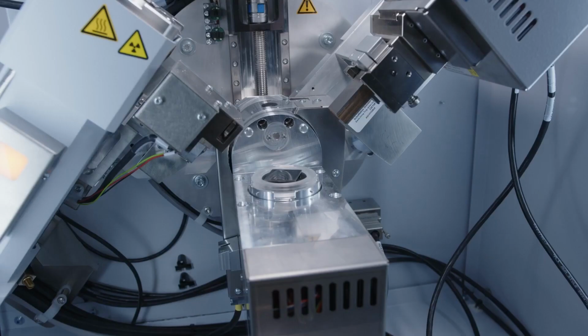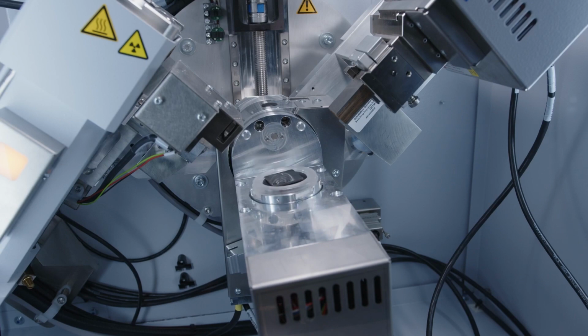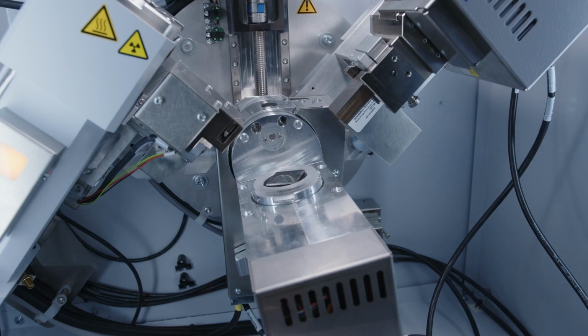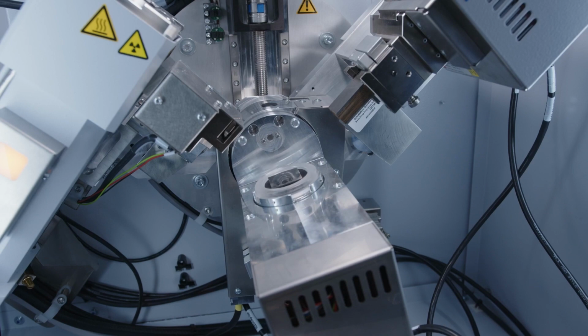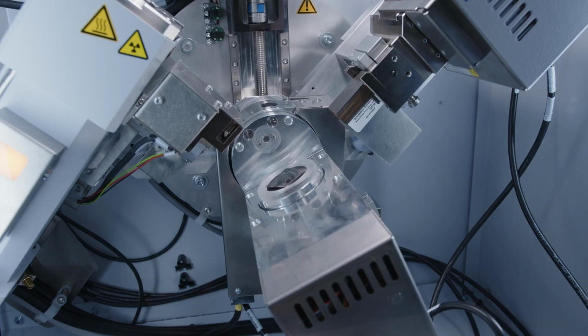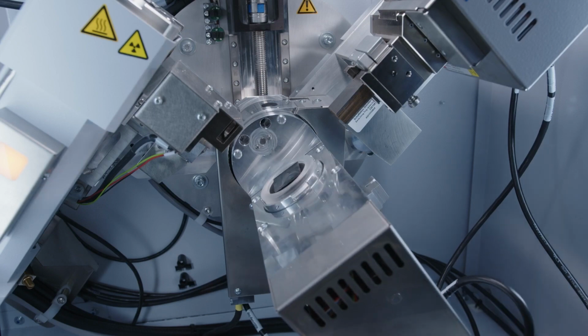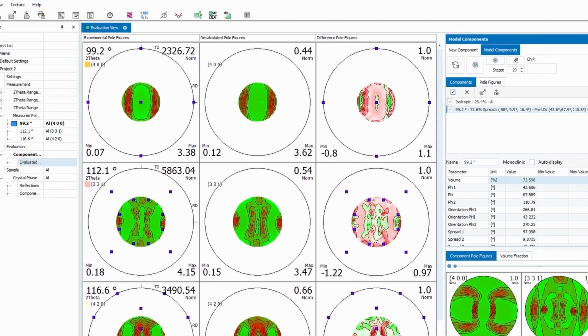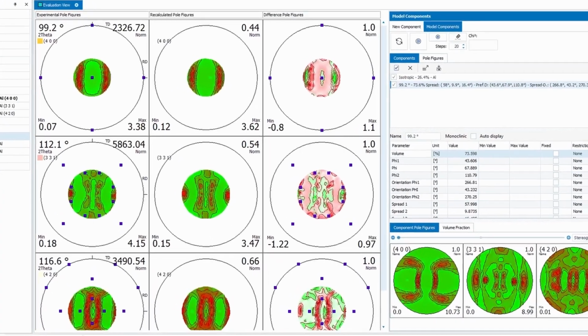The 2 theta for a peak of interest is selected, and a series of phi scans at different sample tilts are collected. These scans are plotted in a polar coordinate system, resulting in a graph called the pole figure. The measurement is repeated for several diffraction peaks. The pole figures are then loaded into diffrac.texture, where the overall orientation distribution for the sample is calculated. Advanced techniques like grazing incidence diffraction, X-ray reflectometry, residual stress, or texture analysis were only possible in floor standing system equipment in the past. The D6 phaser with a universal stage brings the measurement into the benchtop system domain.